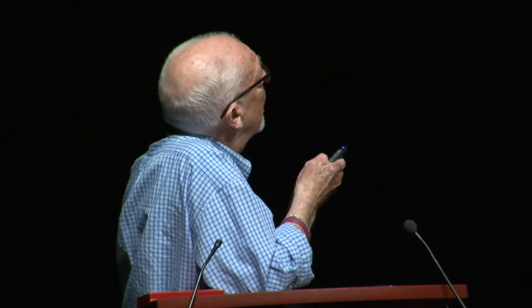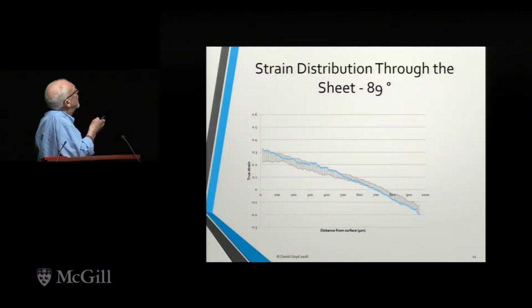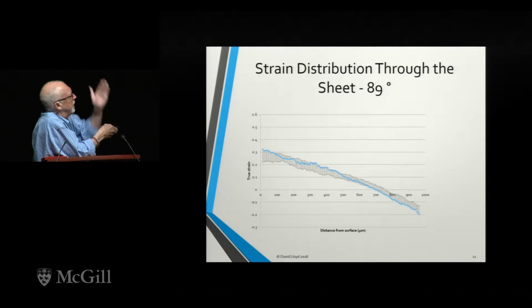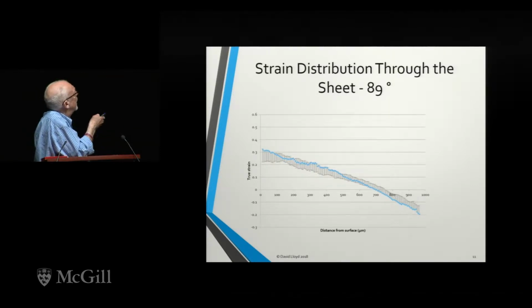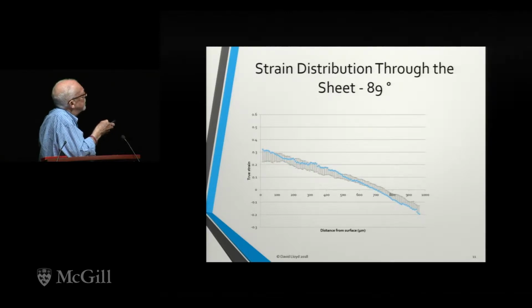These are the upper and lower limits of the strain measurements that were made. These are not multiple samples, it's a single sample. What we're basically doing is concentrating around the apex of the bend and moving either side of that to get the range of strains. You can see that the scatter is of the order of a strain of about 0.1 when you're close to the surface, and it generally decreases as you go into the bulk of the sample.